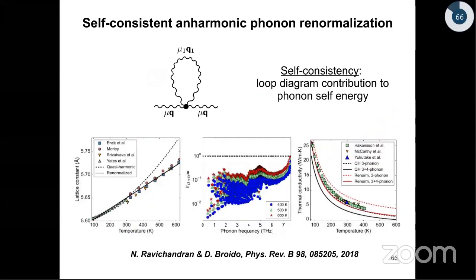So we developed a self-consistent renormalization framework to fix this issue. This renormalization scheme was based on this loop diagram that I think you're all familiar with. And when we included this renormalization, we not only got excellent agreement with the experiments for lattice constants, the phonon quasi-particle picture is now well behaved. Gamma over omega is much lower than 1 for most phonons. And the thermal conductivity that we get, that is the red solid curve on the figure on your right, lies very close to the experimental data.